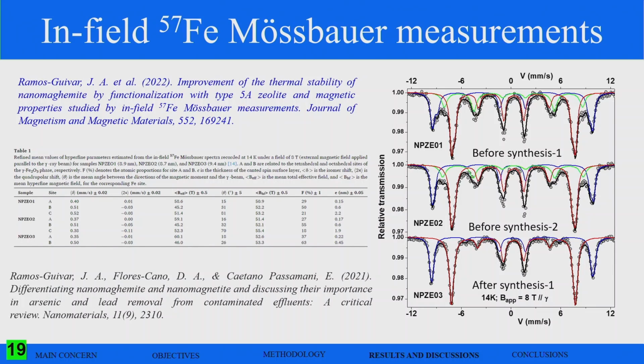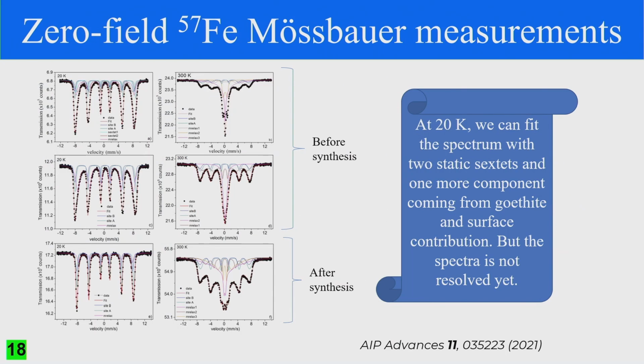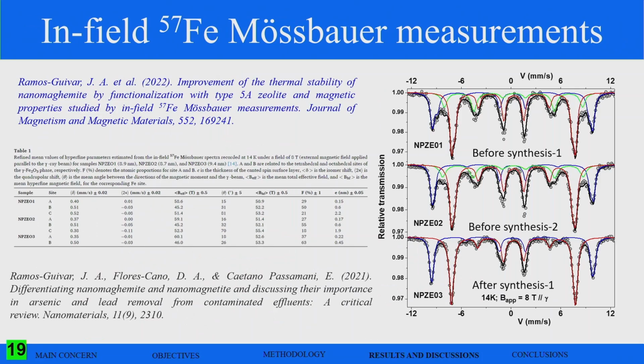Of course, when we do the after-synthesis procedure, when the maghemite was already grown and separated from the zeolite independently, we can see that the spectrum has the same trend as at room temperature. Here, as I told you, two sextets can easily be used to fit. And that is confirmed using the in-field Mossbauer spectroscopy. So this is the final solution I think we have found.